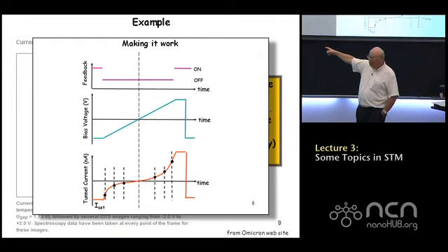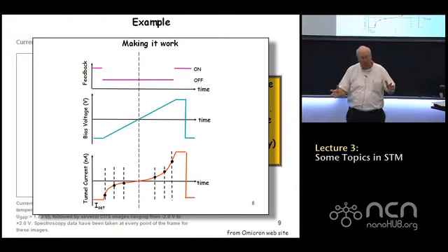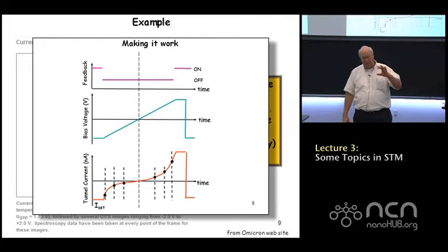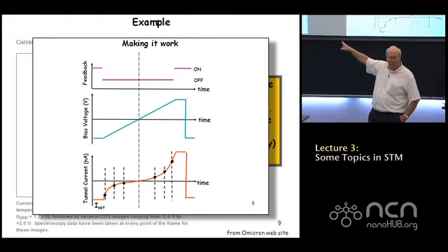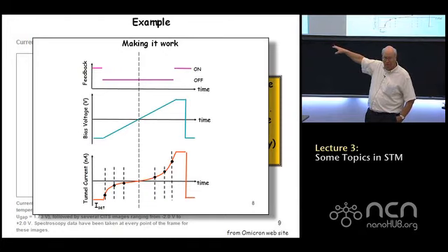If you see the current is suppressed near V equals 0, of course when V equals 0 there's no current that flows. But if there's a true band gap in silicon, as you bias the tip with respect to the substrate, no current should flow until you hit either the conduction band or the valence band edge. That's when the tunnel current would pick up and start to increase above I equals 0 on this diagram.